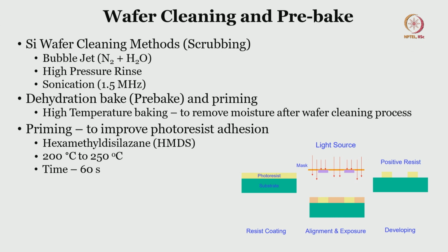The wafer cleaning and pre-bake includes silicon wafer cleaning methods, which are scrubbing, bubble jet N2 plus H2O, followed by high pressure rinse, sonication, then dehydration, which is pre-bake, high temperature baking to remove moisture after the wafer cleaning process, and priming, which improves the photoresist adhesion onto the wafer. It uses HMDS, heated between 200 and 250 degrees centigrade for 60 seconds. So, this is what happens in terms of wafer cleaning.